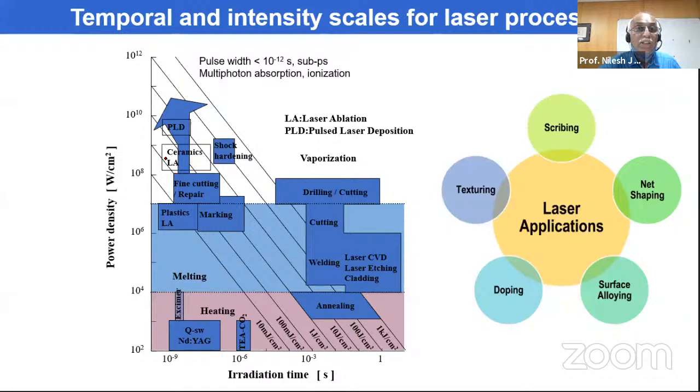Today, I will mostly describe nanosecond pulse-width approaches used for texturing, scribing, surface alloying, and doping. In some cases, we also use femtosecond lasers, and I'll try to describe those as well, connecting them to future research for functional device fabrication. The key parameters are wavelength — connected to photon energy and material absorption — focal length of the lens affecting feature size, beam shape affecting energy distribution, beam energy and pulse width determining heat-affected zone, depth of focus for aspect ratio, and the medium of processing.